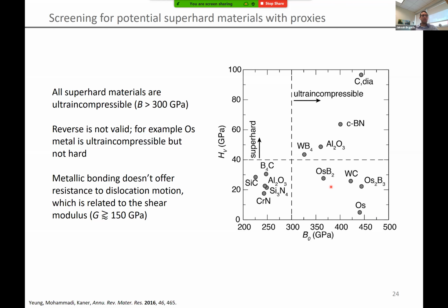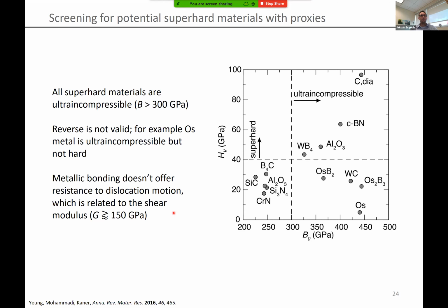In the field, this would be related to what's known as resistance to dislocation motion. You're essentially preventing dislocation or the movement of atoms. Now, there's no easy way to measure dislocation motion, at least at the first principles level, but there is a relationship between dislocation motion and shear modulus.